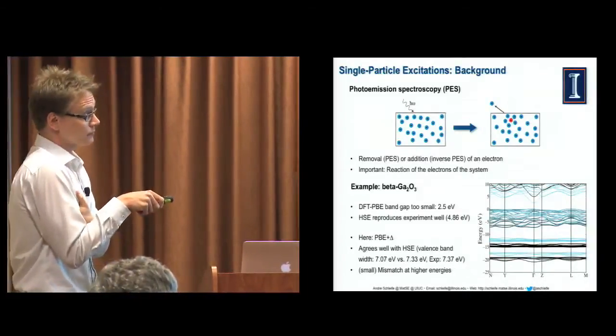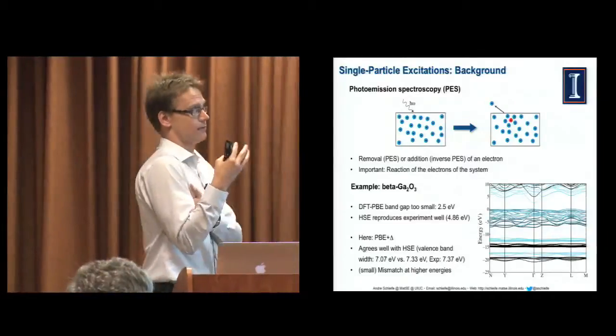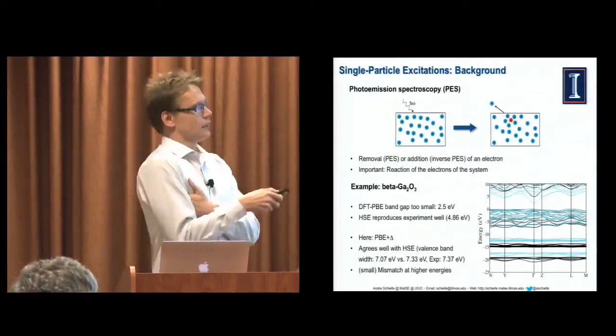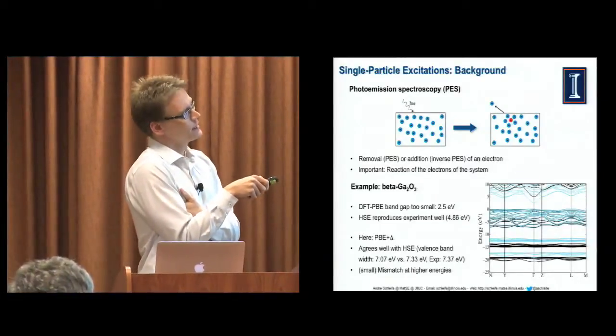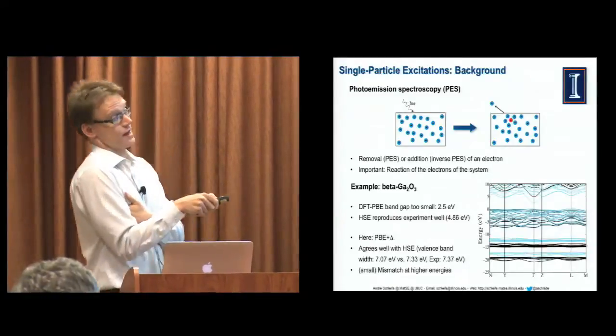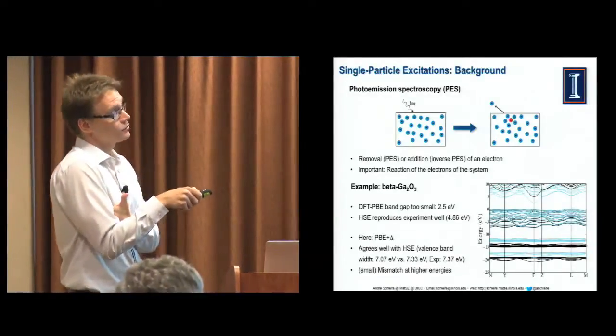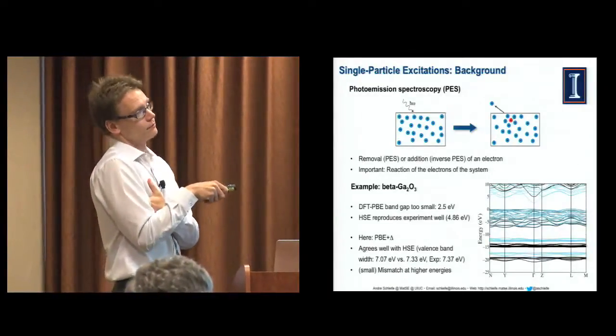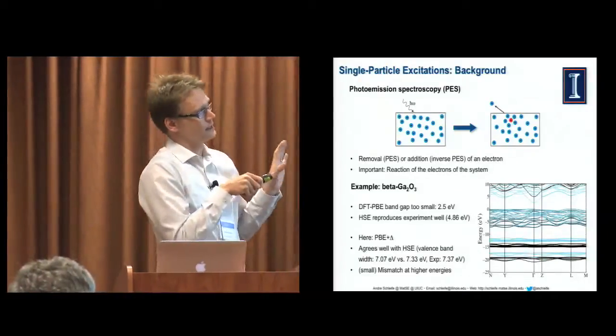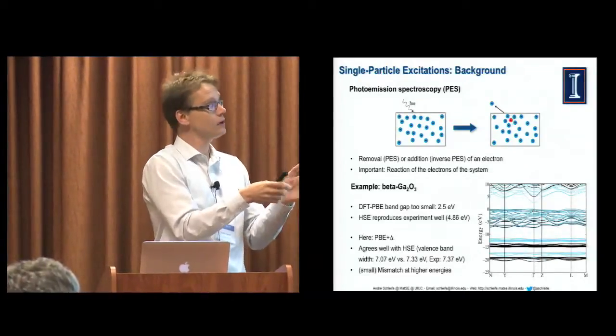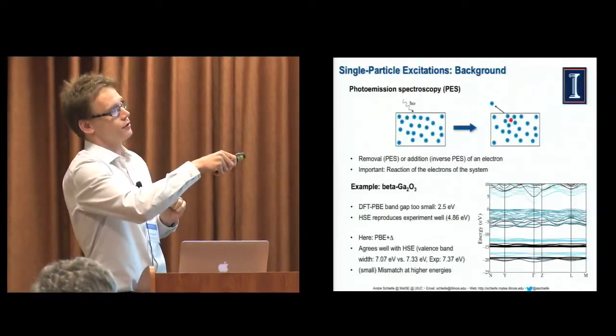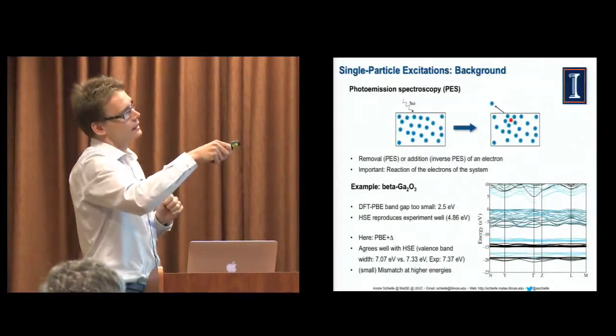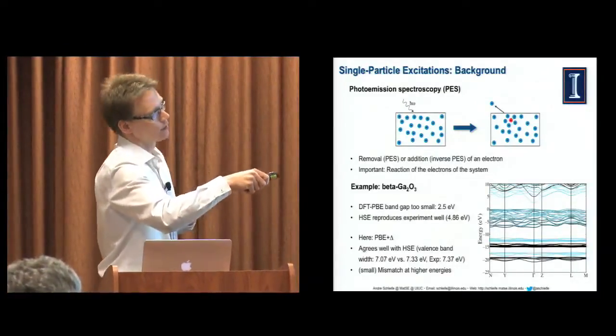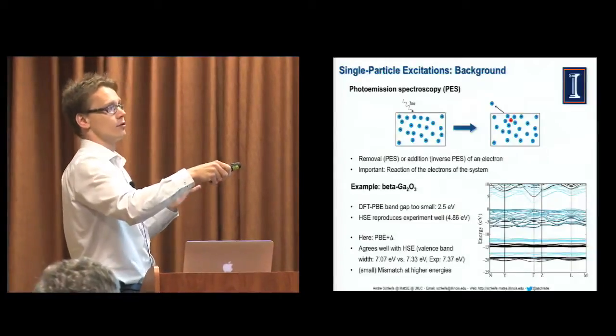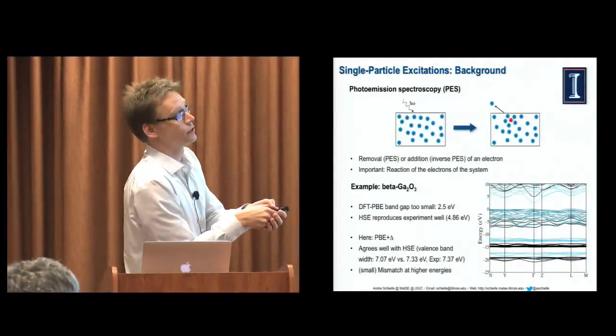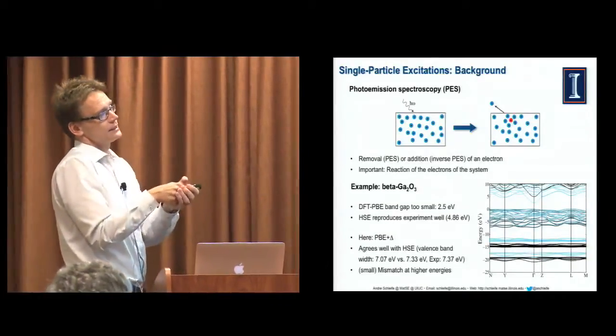Okay. So now in order to understand how to model, how to compute a band structure, we have to see what is the experiment that one carries out when you measure that quantity. And in the case of a band structure, that would be photoemission spectroscopy. And so in this experiment, what you have is a sample, right? Your sample of your material, and a high energy photon. So this is, in this case, maybe X-rays. Comes in and excites an electron so that the electron actually leaves the material. And so what remains behind is a positively charged hole. And this process is what we want to model.